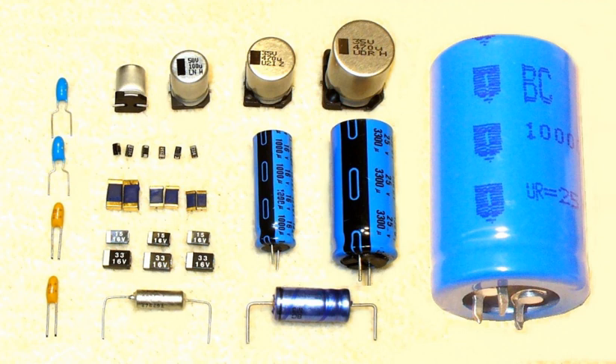In non-solid electrolytic capacitors, the heat generated by the ripple current forces the evaporation of electrolytes, shortening the lifetime of the capacitors. Exceeding the limit tends to result in explosive failure. In solid tantalum electrolytic capacitors with manganese dioxide electrolyte, the heat generated by the ripple current influences the reliability of the capacitors. Exceeding the limit tends to result in catastrophic failures with short circuits and burning components. The heat generated by the ripple current also influences the lifetime of aluminum and tantalum electrolytic capacitors with solid polymer electrolytes. Exceeding the limit tends to result in catastrophic failures with short circuits.